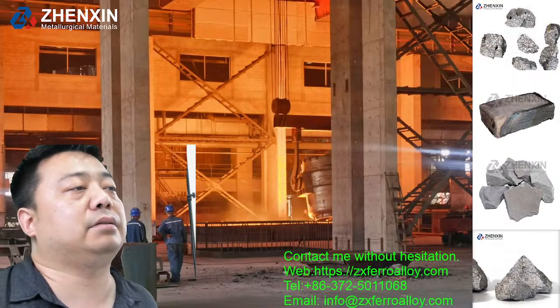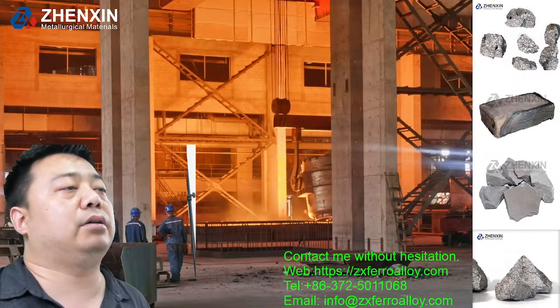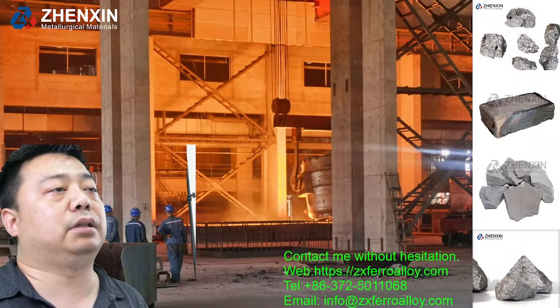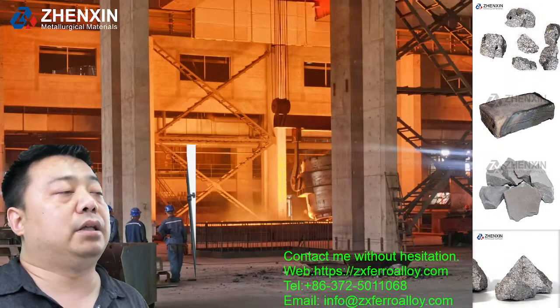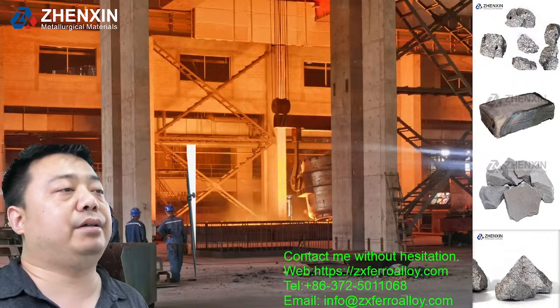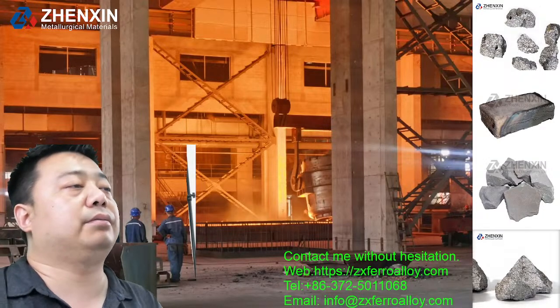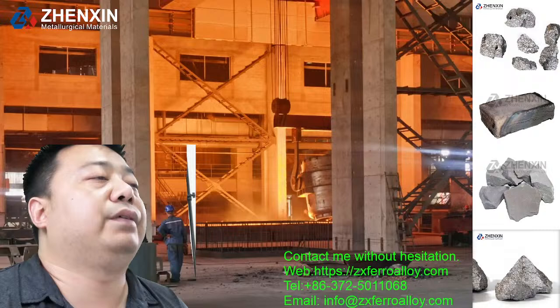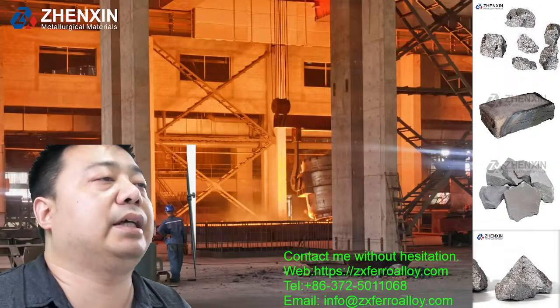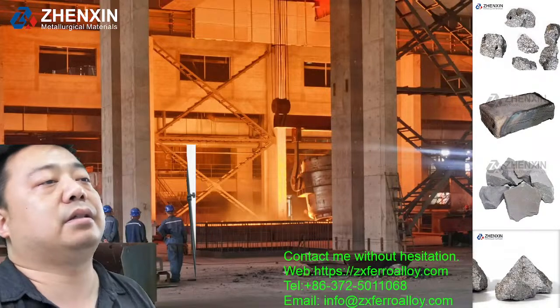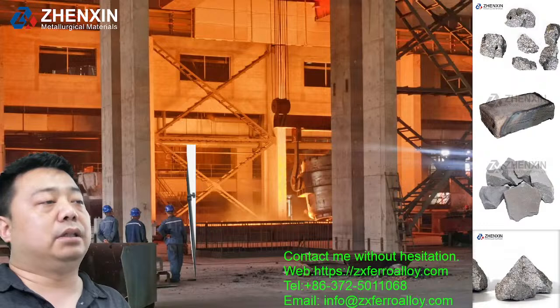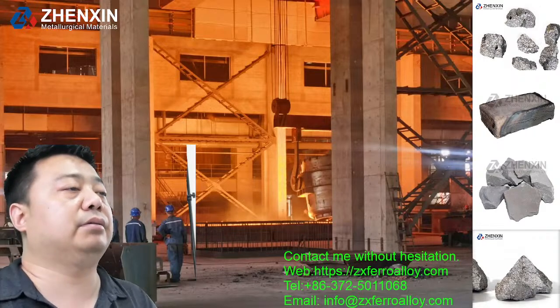The use of calcium silicon cored wire can reduce the temperature loss of molten steel to 5 to 7 degrees per minute, which is 3 to 6 times lower than before. The use of calcium silicon cored wire with different ratios of silicon and calcium can precisely adjust the chemical composition of the molten steel.